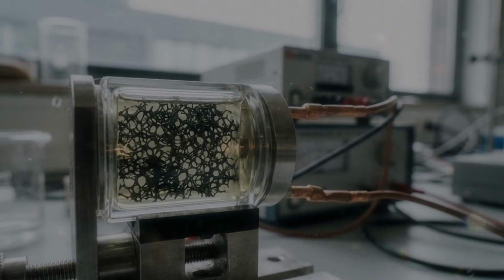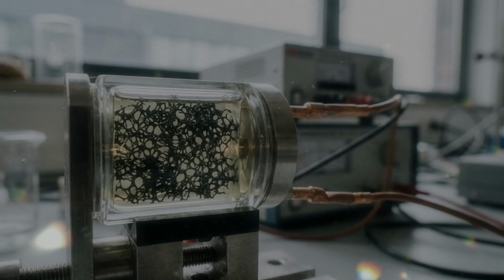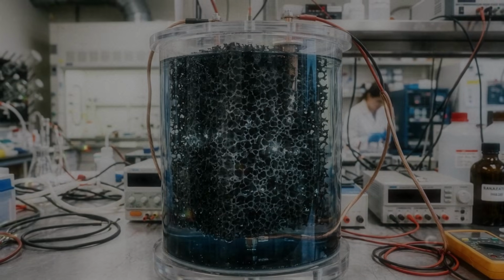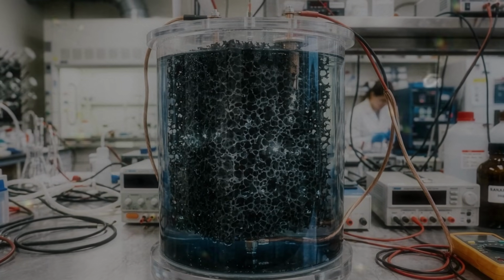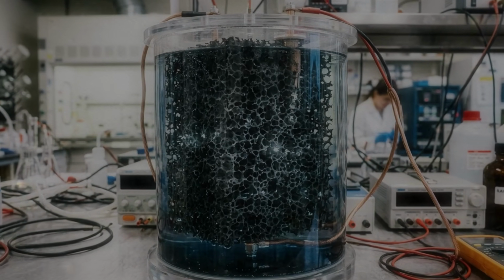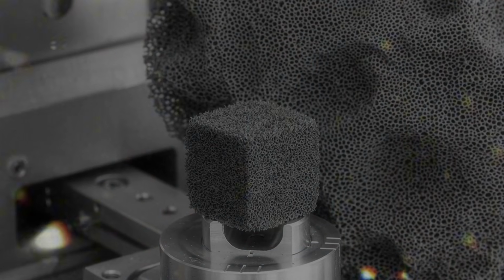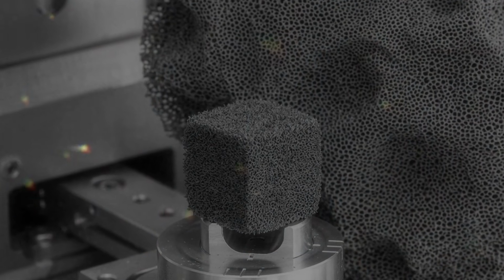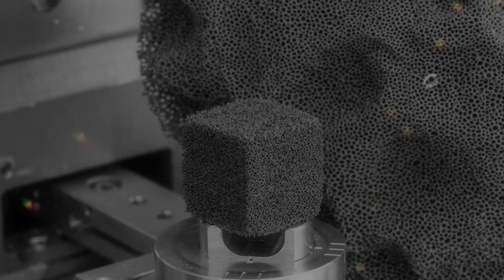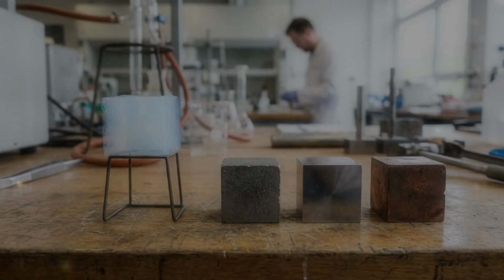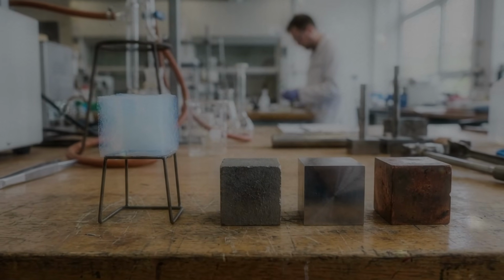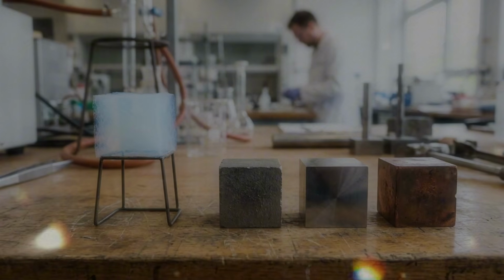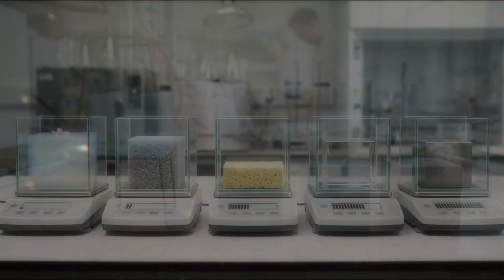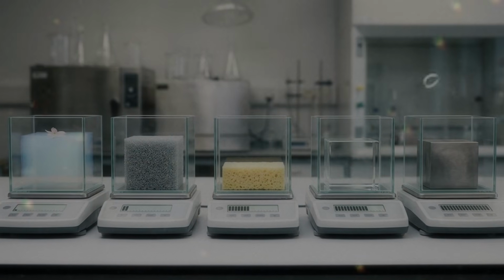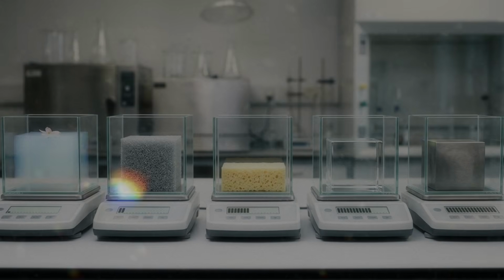Combining functions is difficult because the best structure for heat may not be the best one for sound. Tiny pores restrict gas movement and improve thermal insulation. Larger connected pores may absorb certain sound frequencies more effectively. A rigid structure can reflect sound but may crack. A soft structure can absorb vibration but may conduct heat differently. Engineers adjust density, thickness, pore size, and supporting layers to find a useful balance.